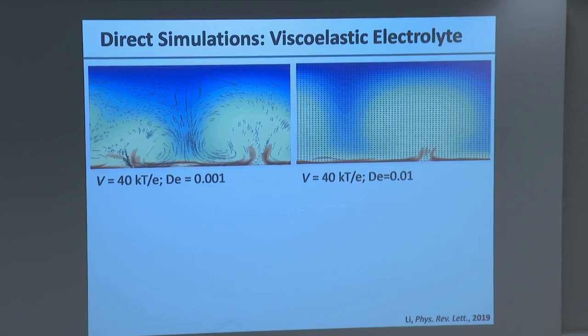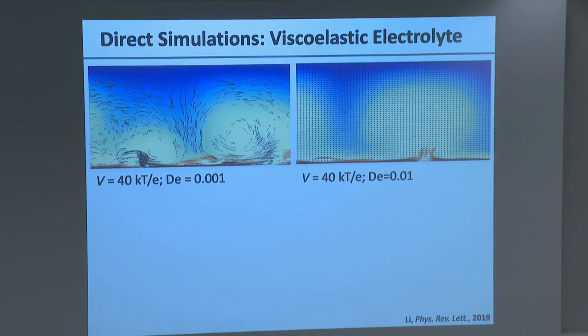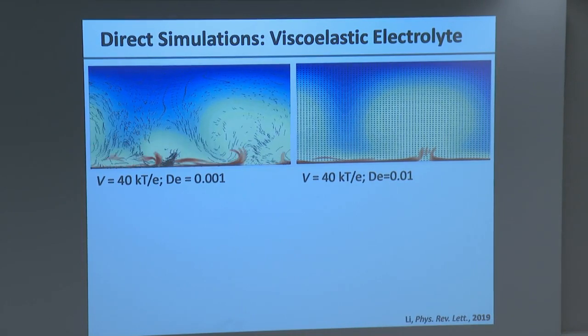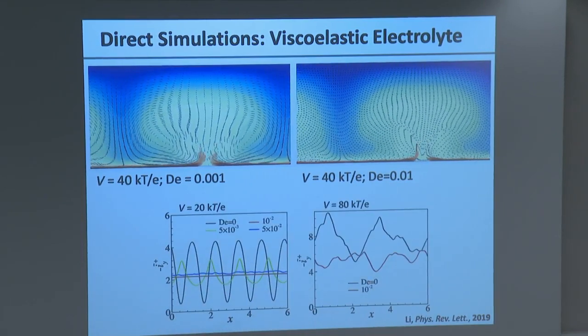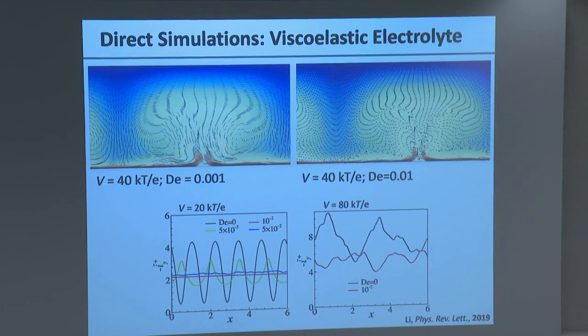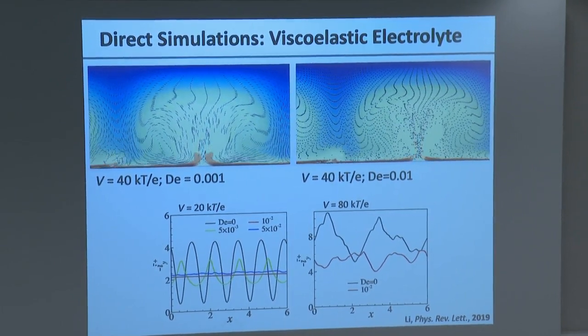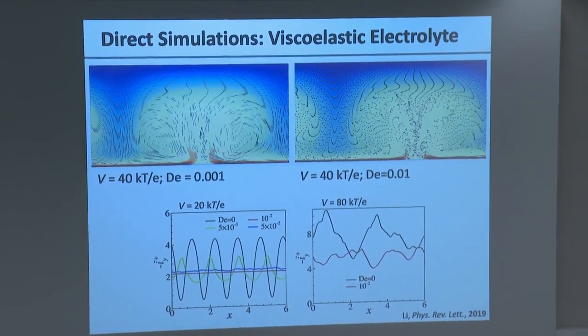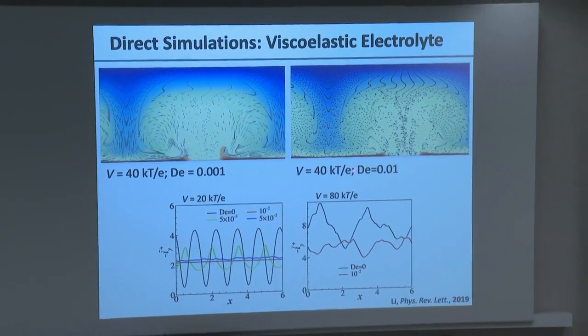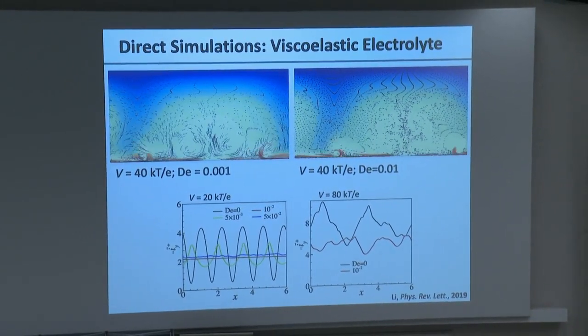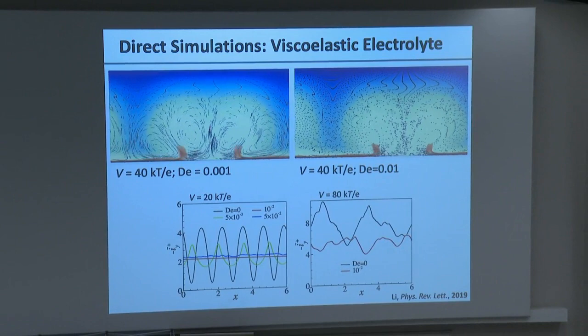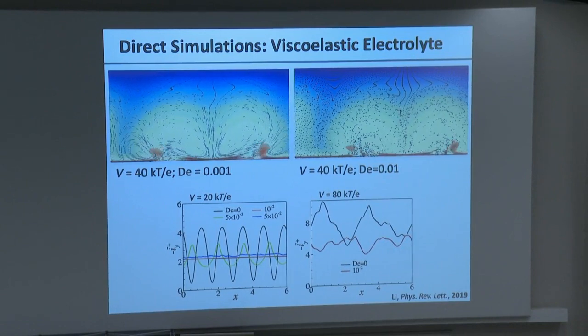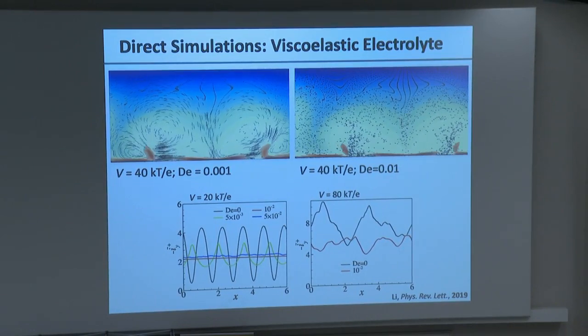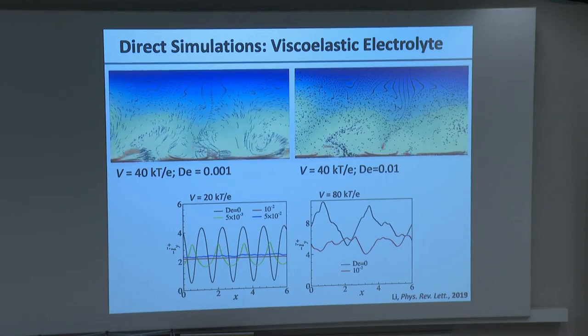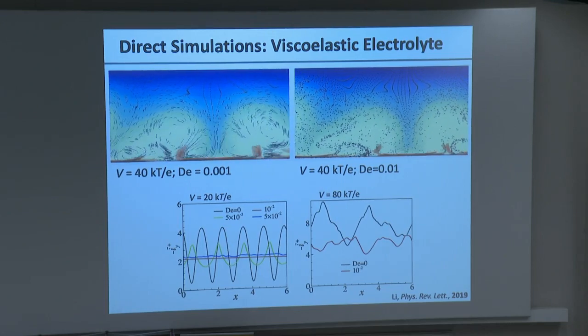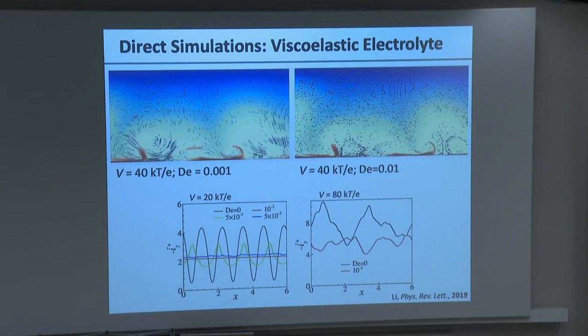But then what is occurring is that even before the fluid stops coming down, the polymer relaxes and then moves again, with the end result that the polymer causes a kind of chaotic flow of its own near the interface, producing, and it's more apparent in the case of high polymer concentration, a kind of backflow that homogenizes the downflow of ions towards the interface. And in so doing, we believe, homogenizes the deposition of the metal at the interface.